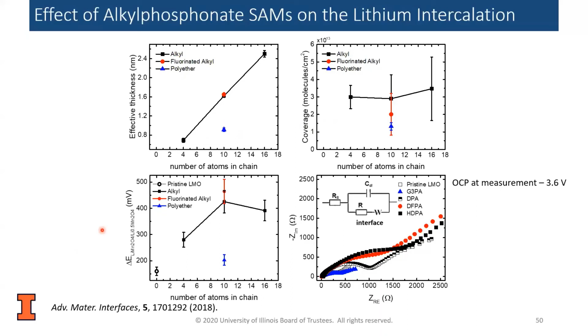Okay, so if you look down here, these are the differences in the delta E, or that is the amount of charge transfer. This is the pristine LMO. So the default value for the delta E would be about 150 millivolts. So we could see that we do increase the delta E value. That is, we decrease the ability to do charge transfer by putting the SAM on the surface. Okay, we could see here that the polyether did not very much increase the delta E. So we're getting about the same amount of charge transfer as the bare LMO. And this is another kind of confirmation that it doesn't look like the polyether is making a very thick chain.